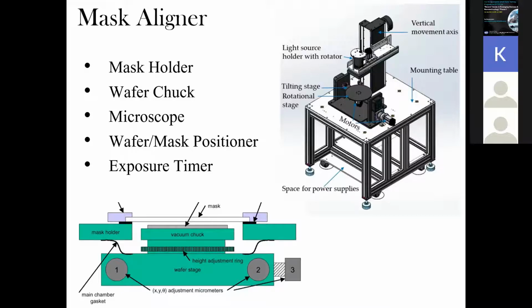Now this also depends upon the resist thickness. If your resist thickness is more, your timing should be more, but it is always better to have a thinner resist with a lower time if you want to achieve a lower dimension. If you want to achieve a dimension of, let's say, 100 micron or so, then your resist thickness can be more and timing can also be more. But otherwise, if you want to go for a lower dimension, always try for a thinner photoresist, and your exposure time should also decrease accordingly.